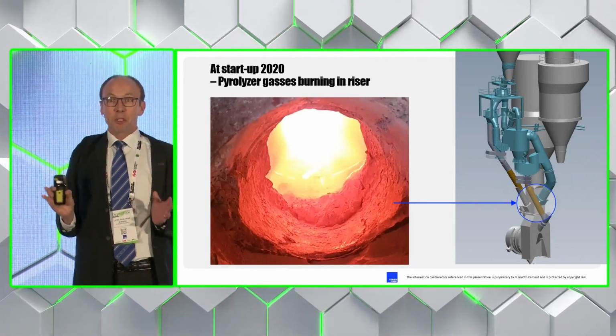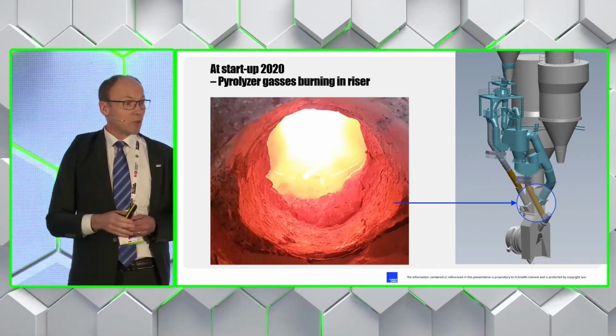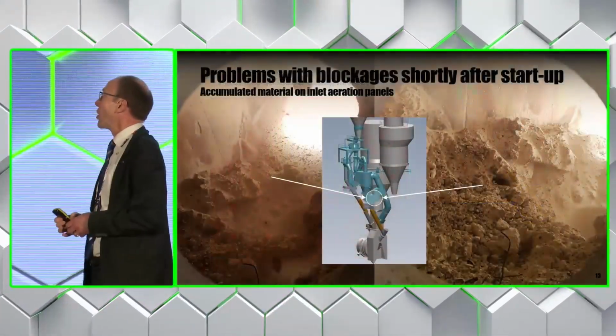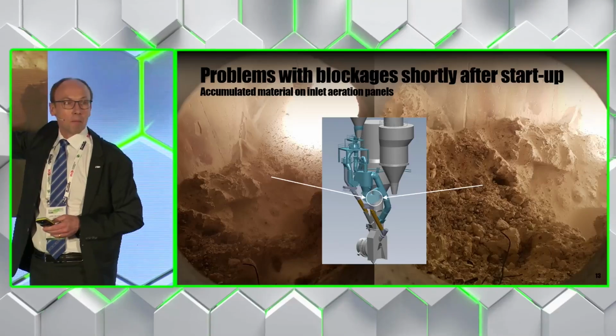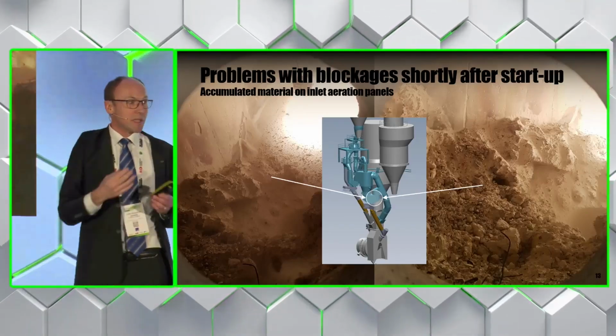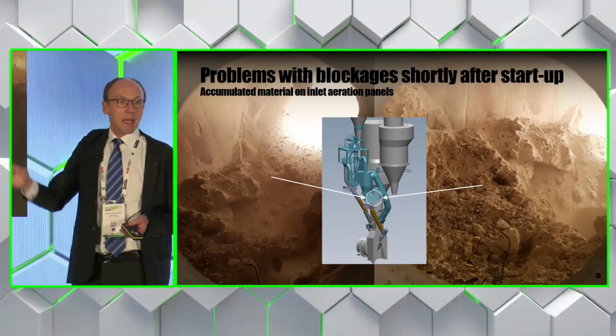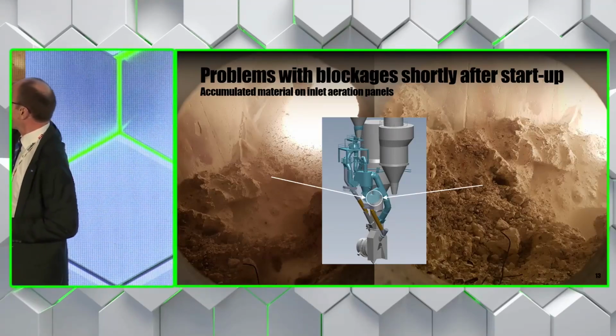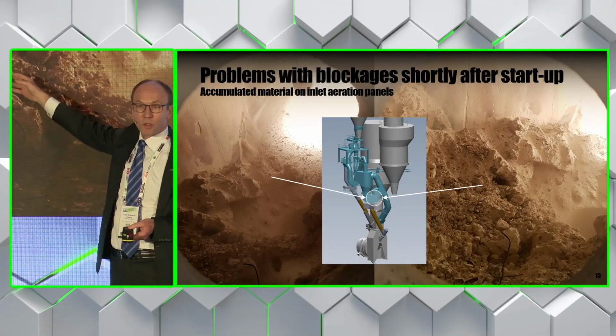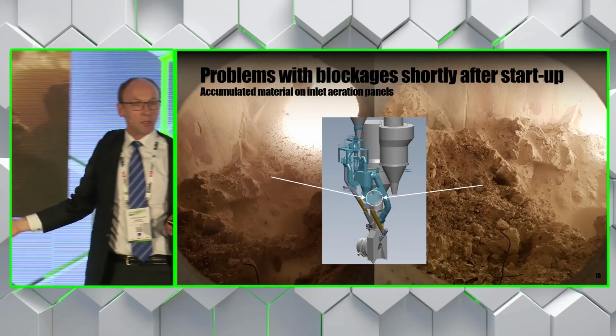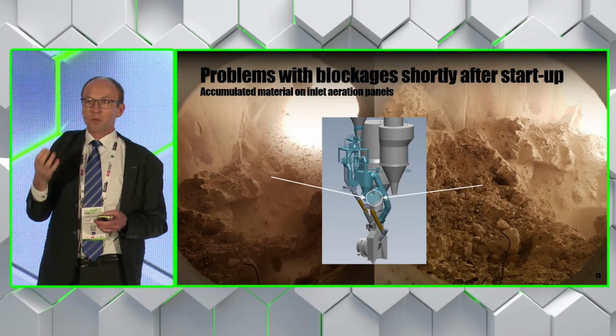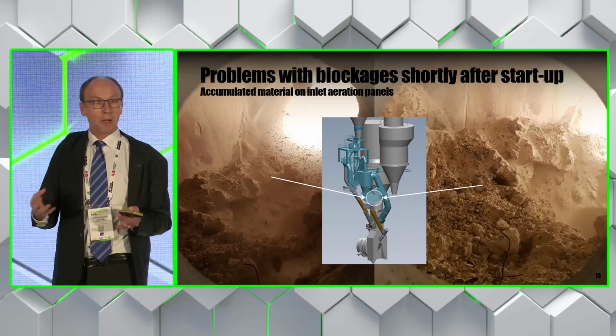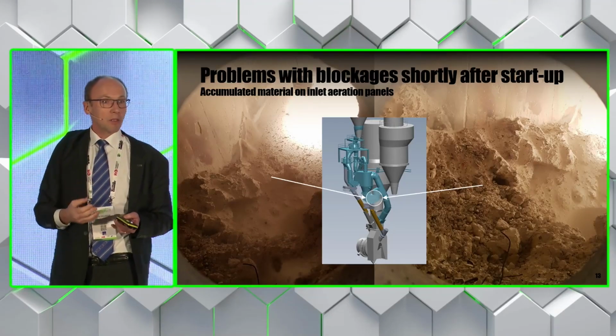But then after about 2 weeks, we really got into trouble, because now the whole pyrolyzer blocked up with buildups. This was the debris I talked about before. It started sedimenting out in the process. Here you can see wires and stones and things like this sedimenting out in the process. And we had this extremely corrosive environment with sulfur and chlorine at 800 degrees.